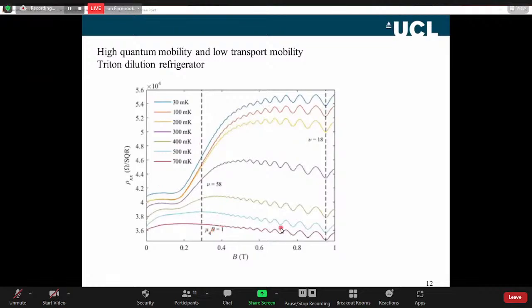If we look at the oscillations and measure where they start in the field, we have a condition μ times B equals 1, where μ is the mobility and B is the field. We know in these structures that the quantum mobility is very, very high. We can actually see down to filling factor 58, or 58 Landau levels, very clear magnetoresistance oscillations. If you saw this, you might think that your transport mobility would be in the millions.